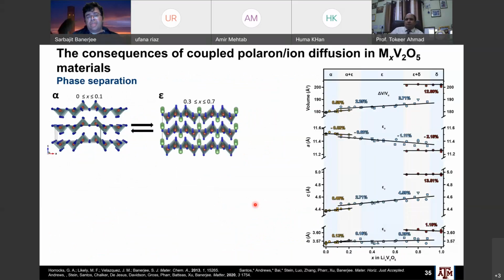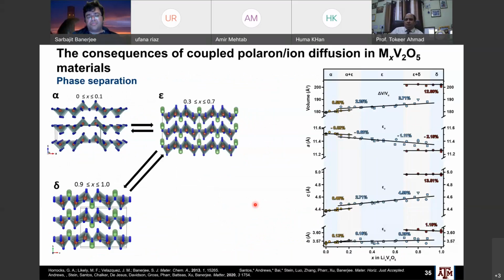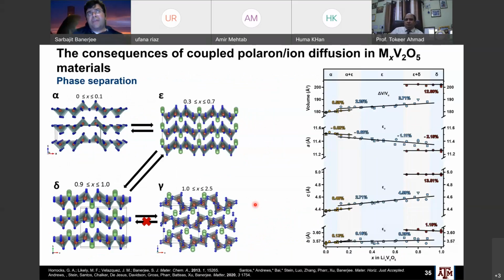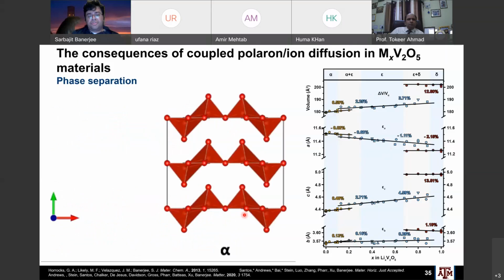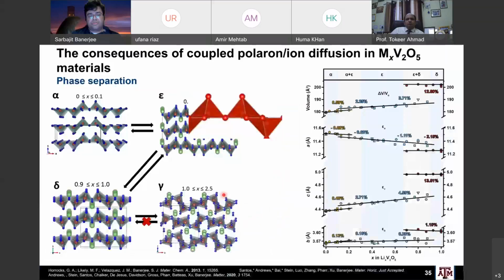Because of this polaron limitation, you end up having this series of phase transformations. And essentially what happens is that as the lithium ion concentration increases, to accommodate the lithium ion concentrations, these higher, more distorted phases are formed, and you end up inducing these diffusive phase transformations. So this is a phase diagram, and I'm going to show you a video.